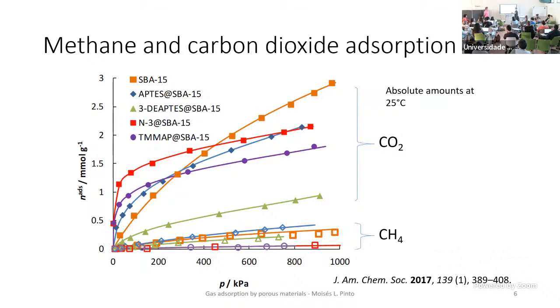Isotherm because all these points were taken at a constant temperature, yes? In this case, 25 degrees. And if you look in here, we have methane and CO2, so we are well above the critical temperature here. For methane, it's much higher, okay? And you have here what? Pressure up to 10 bar, so 10 times above the atmospheric pressure. And we have here the absorbed amount in millimoles per gram.